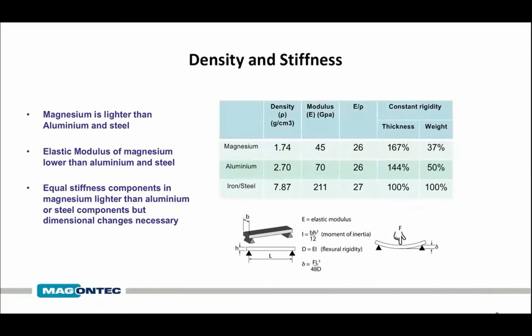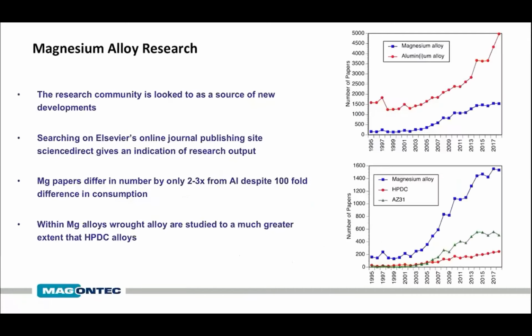But you'll notice that the stiffness and the density are actually proportional. So if you take a ratio of the elastic modulus over density for magnesium, aluminium, and steel, you actually get pretty much the same value. But in most situations we're worried about stiffness in bending, and the stiffness in bending increases with the cube of the thickness. So you can design components in magnesium to be considerably stiffer than in aluminium.